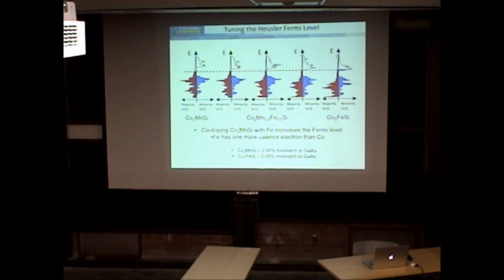Right? Simple model. Now, if you do that, if you look at this, which said this was predominantly the majority of spins were red. If I go far enough to cobalt-2 iron silicon, I'm no longer a half metal, and the majority, and we now should have higher density of down spins if these were up spins. So it should change the spin polarization. And then it should be sort of pretty low when you're in the middle here, when you've moved these things up. Okay, so that was sort of a thought.